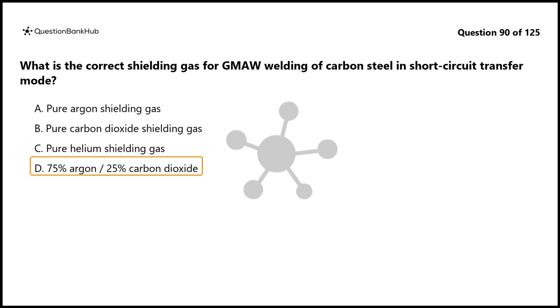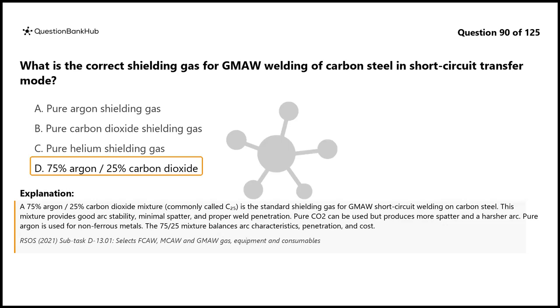The correct answer is D. 75% argon over 25% carbon dioxide. A 75% argon over 25% carbon dioxide mixture, commonly called C25, is the standard shielding gas for GMAW short-circuit welding on carbon steel. This mixture provides good arc stability, minimal spatter, and proper weld penetration. Pure carbon dioxide can be used but produces more spatter and a harsher arc. Pure argon is used for non-ferrous metals. The 75/25 mixture balances arc characteristics, penetration, and cost.